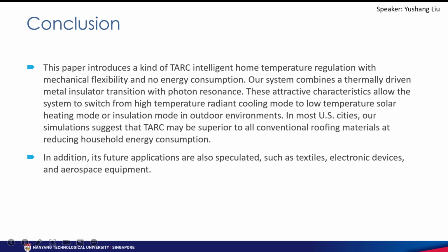In conclusion, this paper introduces a kind of TARC for intelligent home temperature regulation, with mechanical flexibility and no energy consumption. Our system combines the thermally driven metal insulator transition with photonic resonance. These attractive characteristics allow the system to switch from a high-temperature radiative cooling mode to a low-temperature solar heating or insulation mode in outdoor environments. In most US cities, our simulations suggest that TARC may be superior to all conventional roofing materials at reducing household energy consumption. In addition, we also predict its future applications, and the application prospect is fabulous.